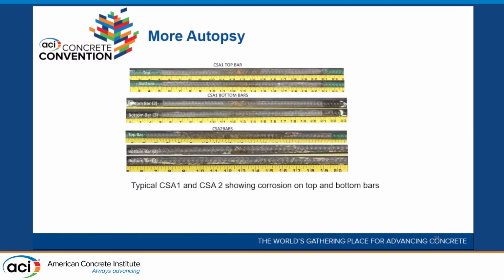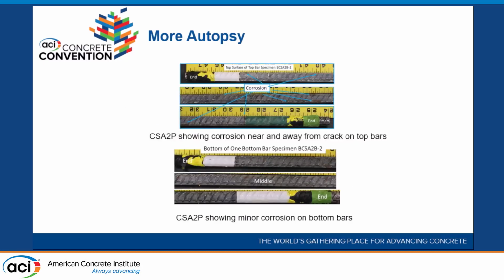And here's looking at CSA1, and we got CSA2, and you got corrosion. Even though they had lower macrocell currents, they had corroding bottom bars in some cases, pretty bad. So once again, in some of these cases, there's no chloride down there, so the bars shouldn't be corroding. Some more autopsies. The polymer version that we had did much, much better, but it still had some little specks of corrosion, and some on the bottom bars again, and the same thing, minor corrosion on bottom bars, away from the cracks.